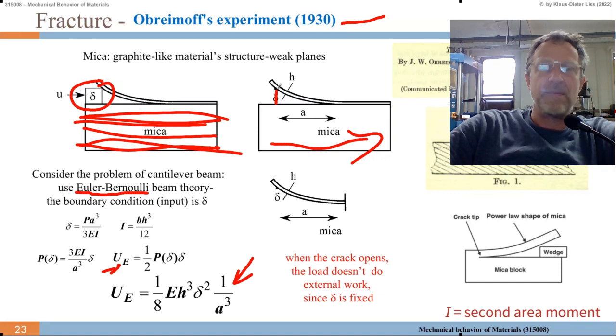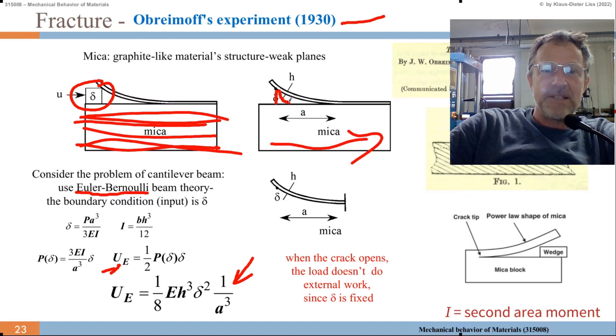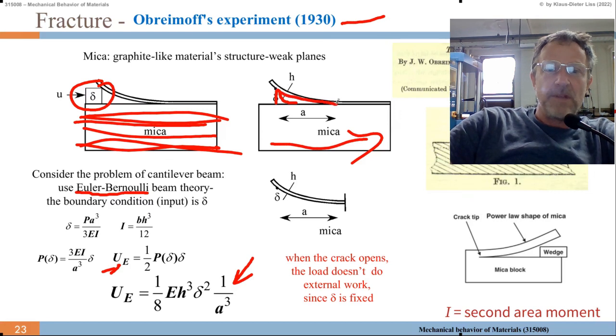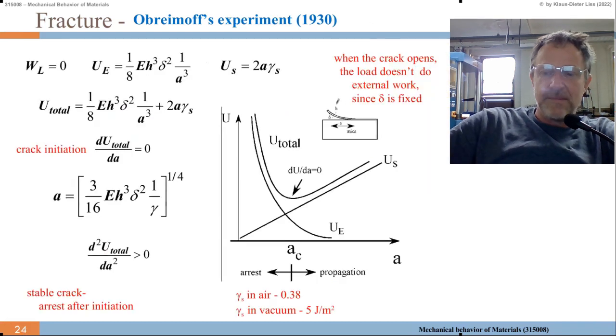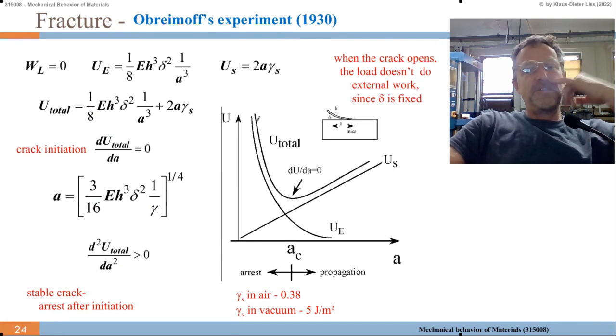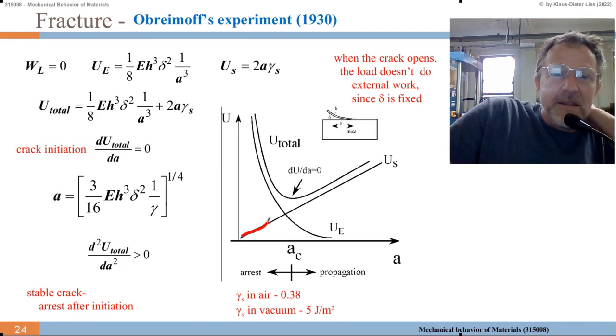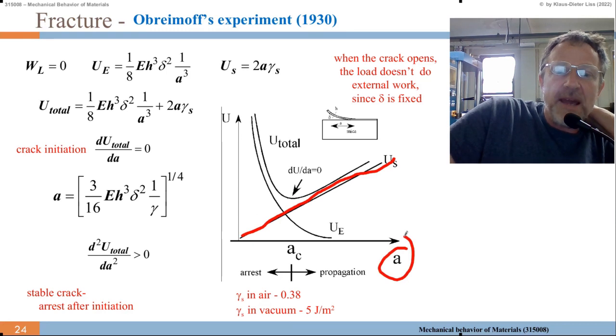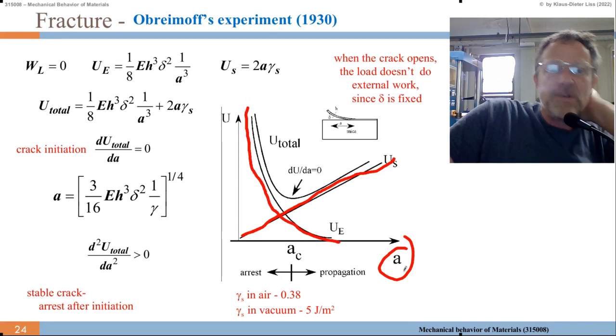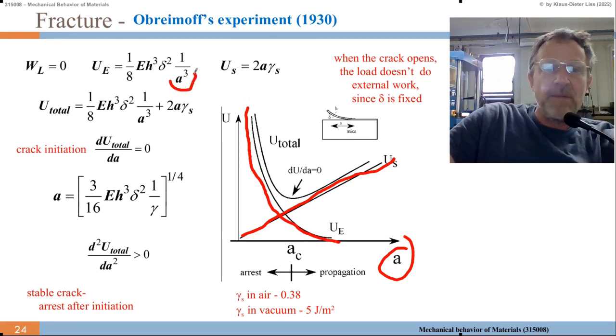This I just lifted up by delta, not more, not less. And then maybe I start with a crack which is like this. That means the crack will grow, so it will grow until - we show it here - the surface energy goes up with larger A, and we just calculated the UE goes down with larger A, with the third power, 1/A to the 3. All the others are constant.